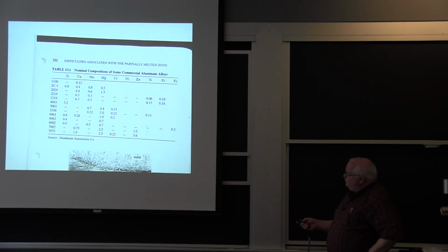1100 is pure aluminum. The 2000 series is the aluminum copper alloys. 4043 is a welding filler metal mostly. 5083 is non-heat treatable. 6061 and 7000 series, these are all heat treatable. Turns out the heat treatable ones have more alloy content. They have magnesium or silicon or copper. The 2000 series is also heat treatable.